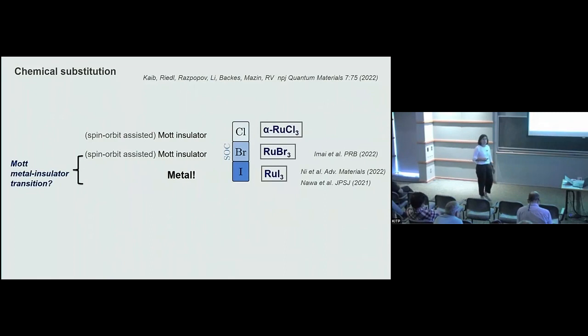In the last 2 years, there has been some synthesis where, instead of considering ruthenium trichloride, you grow the system either with bromine or with iodine. Ruthenium bromide is a work by Imai and collaborators. Basically, this system is also a Mott insulator. However, the big surprise is when you put an even bigger halogen, you take iodine, and the observation is that the system is a metal. So what's going on here?